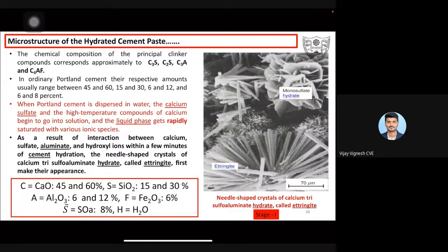The chemical composition of principal clinker compounds corresponds approximately to, for example, calcium oxide, CaO, we can call it as C, 45% to 60%. SiO2, we can call it as S, 15% to 30%. Then alumina, we can call it as A, 6% to 12%. Fe2O3, we can call it as F, 6%. And SO3, 8%. H we can call as H2O. Okay. In ordinary Portland cement, the respective amount usually ranges between 45 to 60, and so on.